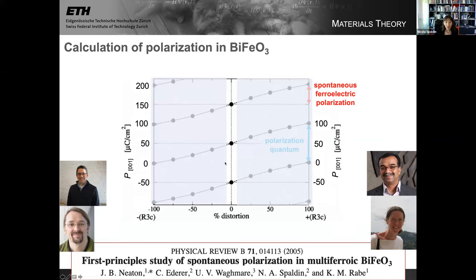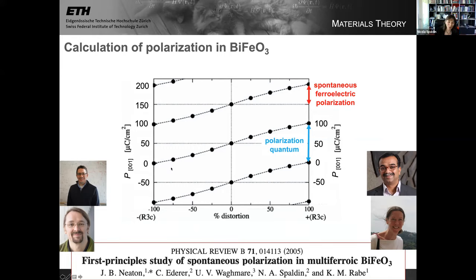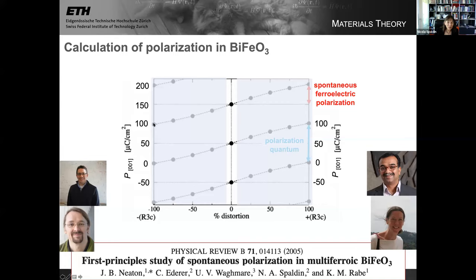And first I want us to look at the undistorted centrosymmetric nonpolar structure and look at the values that one calculates for the polarization. I think this was done using the VASP code. I'm sorry, it was a long time ago, I don't remember. But let's look at the values. For the nonpolar undistorted structure, we see that we don't have zero as a polarization. We have 50, minus 50, 150, minus 150, and so on. So this is exactly analogous to the simple one-dimensional chain that we looked at. The undistorted centrosymmetric structure has a polarization lattice that doesn't contain zero. It contains instead the half polarization quantum, which turns out to be 50 microcoulombs per square centimeter in this case.